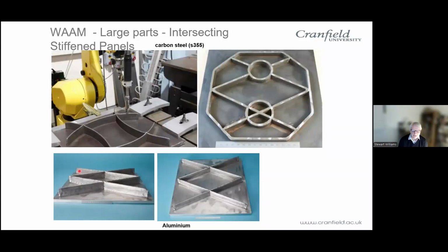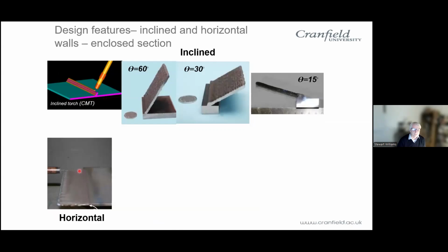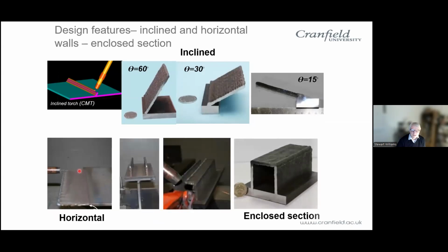intricacies of the process for building complicated parts, looking at things like intersections and crossovers. It's not like machining, of course. In machining, if you go over the same area twice, it's not a problem. It certainly is a problem in additive manufacture because you'll have twice as much material as you need. And we looked at whether we always had to deposit vertically. So we investigated depositing at different angles and found we could actually build structures horizontally if needed, and therefore we could make enclosed sections.